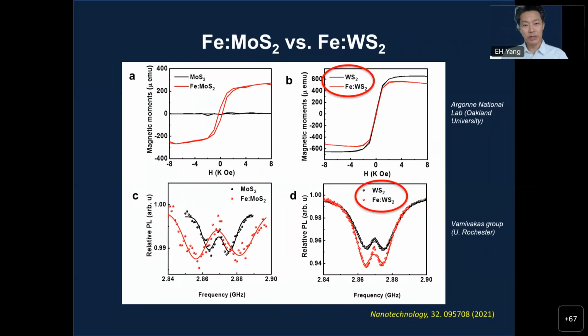The third independent measurement was done at Argonne National Lab this time. It's another SQUID in A and B, and C and D are the same ODMR with the nitrogen vacancy center, but we compare two different materials. One is iron doped molybdenum sulfide, the other one is iron doped tungsten sulfide. The difference here is that you change only the molybdenum to tungsten. However, both of these materials were synthesized in a similar way, right? Only a little bit of difference in the composition of these transition metals, and the temperatures are a little bit different, but the overall structure and overall process are identical.